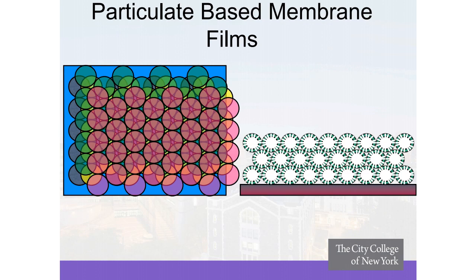Once these particles are formed, they can be assembled through a colloidal assembly process into thin films and forming colloidal crystals, or basically colloidal membranes. And the porosity through these membranes is controlled by the pore size of each one of these particles, which allows the diffusion or the permeation of a gas or of another species of preference through that material. Furthermore, we can functionalize the surfaces and the actual pore surface in such a way that we can also chromatographically separate out materials as they permeate through these colloidal crystal assemblies.